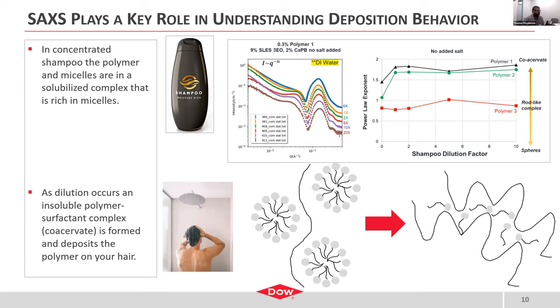However, upon dilution, we see a rapid increase in the slope of the low Q region. That rapid increase in slope at the low Q region upon dilution is indication of a flocculation event where we're actually getting coacervate formation and deposition behavior. You could see here that we studied three different deposition polymers. Two of the deposition polymers showed pretty standard coacervation behavior, where in concentrated shampoo, we had a reasonably low power law exponent, and then increasing dilution showed a drastic sharp uptake in the power law exponent, indicating a coacervate formation.